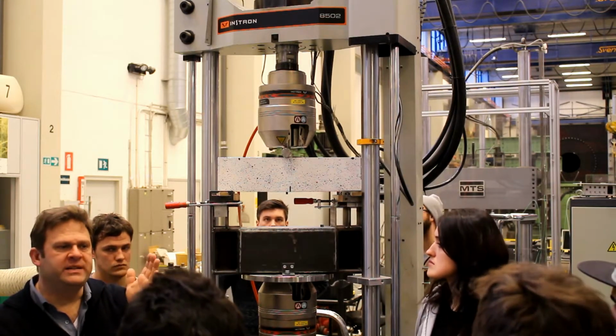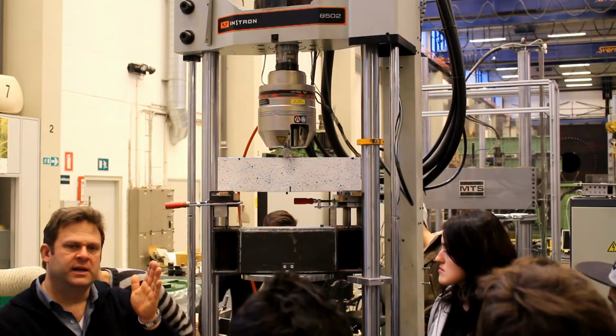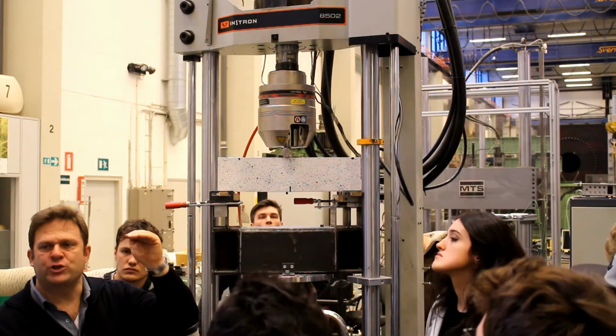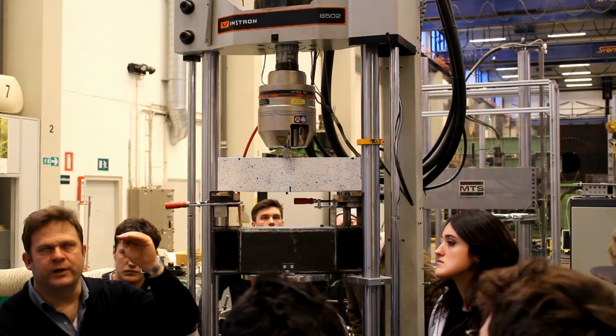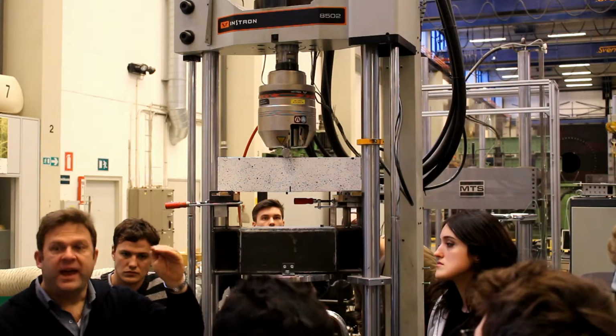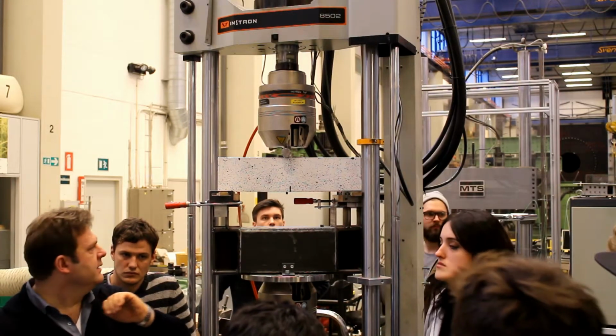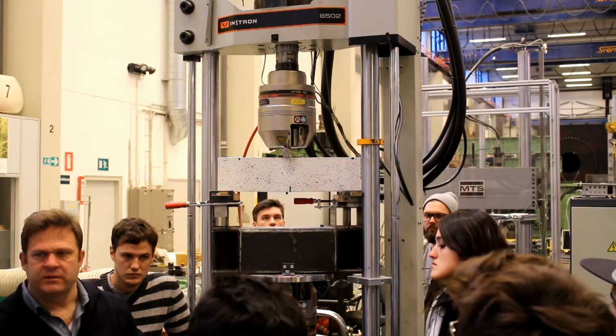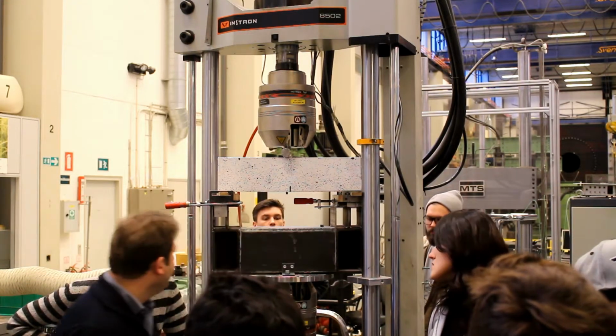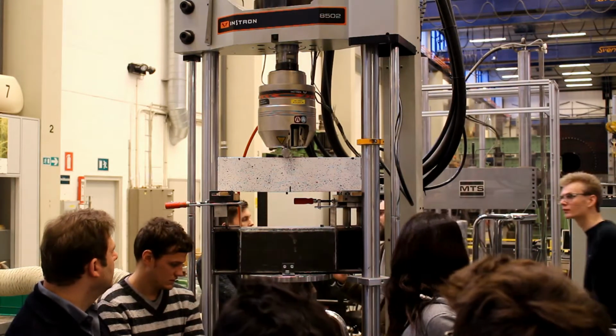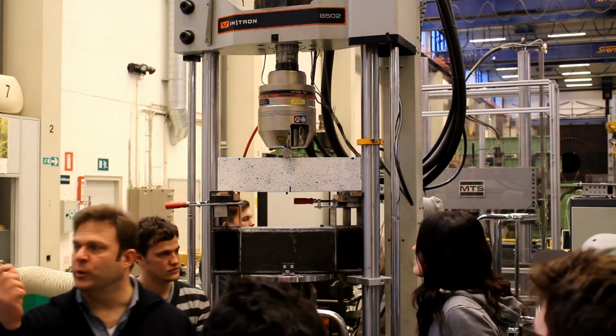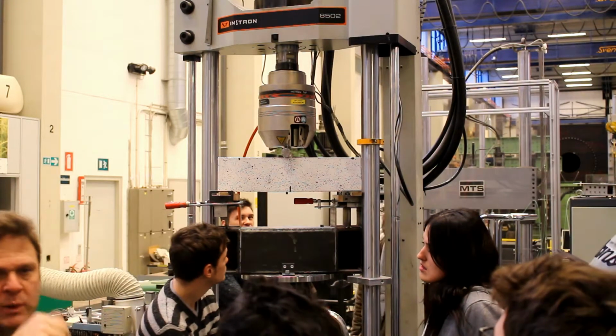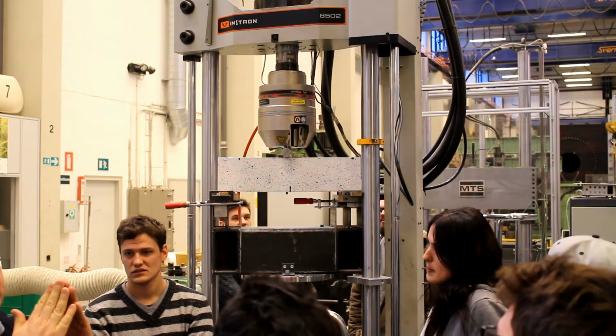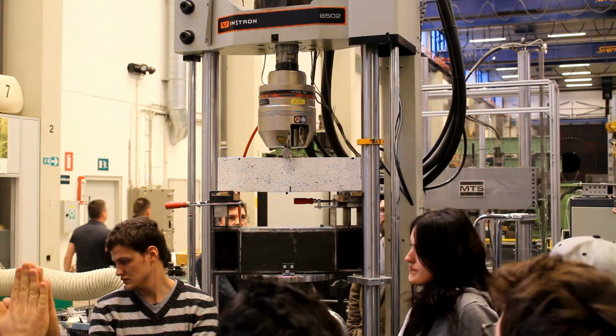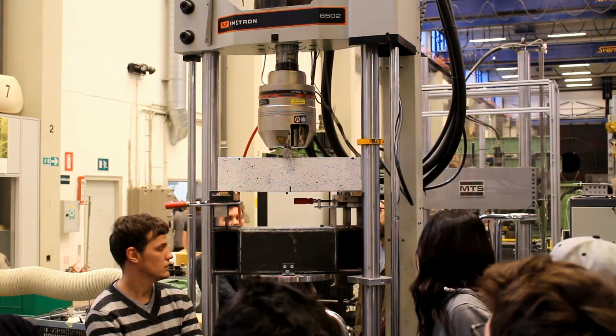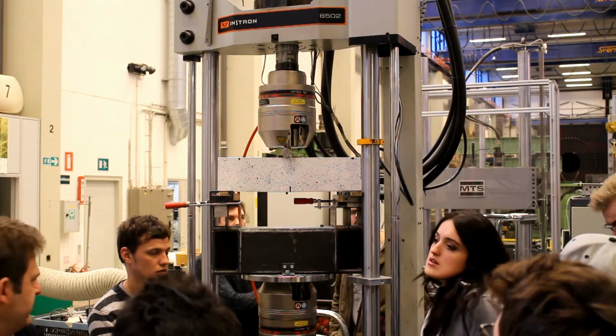The way that the norm tells us to evaluate this material is to find out what is the flexural strength at a crack or a notch opening of 0.5 millimeters and at 3.5 millimeters. So this is how we evaluate these materials. Okay, so now instead of the crack opening, we will run the test up to a deflection of about 4 millimeters. So you can see that the crack continues to open as the deflection continues to increase,